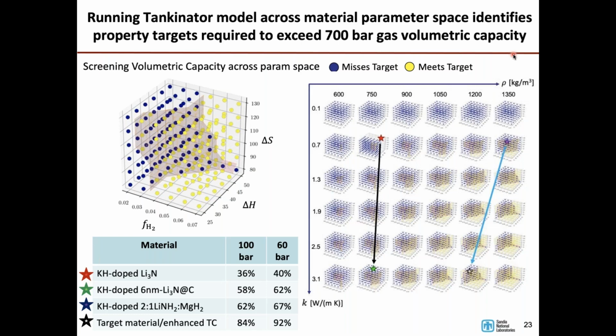That's the purple star. It still doesn't have good heat transfer properties, but we hypothesized that we should be able to improve that by enhancing it with either the nanoscaling or mixing it with a nanoscale high thermal conductivity material. And that's what the blue arrow is showing. That's our target, and we're actually getting pretty close to that right now with a couple of different strategies that we're looking at. So these are not the framework calculations yet. We don't know what the behavior of the fuel cell will be like, but certainly the properties of the tank based on this material are looking very promising.